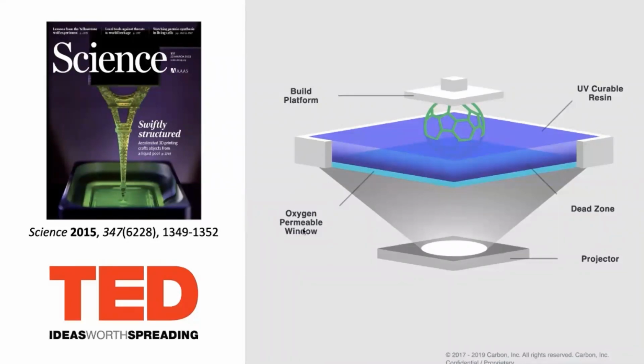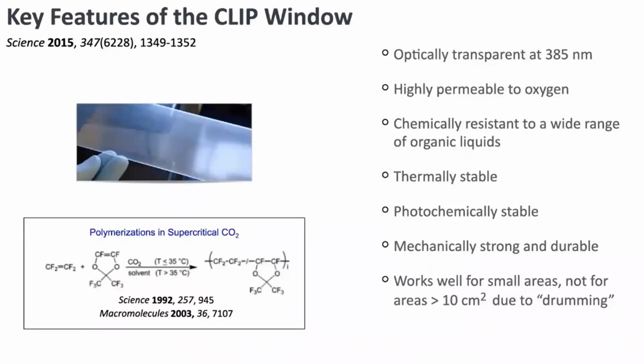And so what happens is when this platform lowers into this reservoir, and maybe it gets within 100 microns of the window and you start to illuminate, that very first layer bonds to the platform, but doesn't bond to the window, because oxygen is coming through the window, and oxygen inhibits the photochemistry that the light is triggering. And so we have an asymmetry right in the beginning where the part bonds to the platform and not the window. And so as you begin to lift up the part, resin can flow in underneath it.